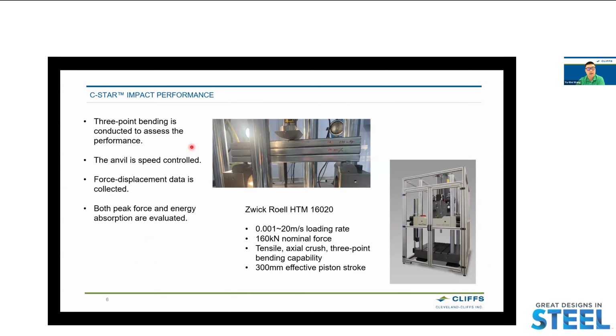So we use the three-point bending to assess the performance. The test setup is very straightforward. We have the anvil in the middle and the supports on the sides. This anvil is speed controlled, force displacement data is collected, and of course, we evaluate the peak force and energy absorption. We use this Zwick Roell HTM testing machine for this purpose. The machine can do from low speed to high speed and is capable of 160 kilonewton nominal force.